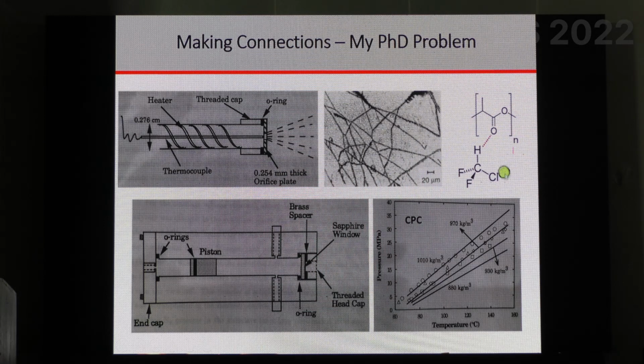And what I was trying to do is to take this, it's actually a gas at room temperature, but you can compress it. It has a certain critical point, a critical temperature and a critical pressure. And you can take this gas and compress it, heat it up a little bit, and it goes into the supercritical region, right? So you take this supercritical gas, and at that state, it still can hydrogen bond with these polymers. So polymers can actually dissolve in a gas, but at higher pressure and higher temperature.